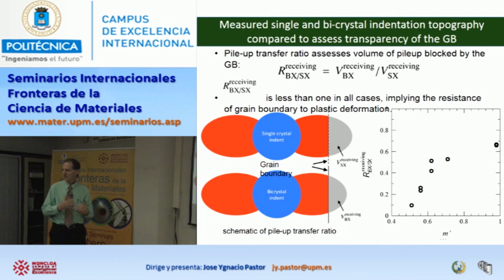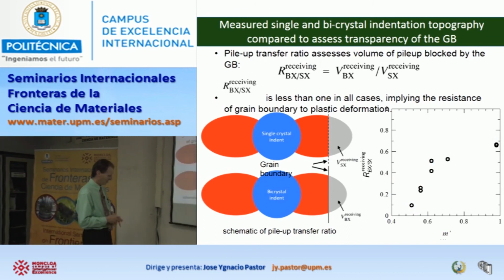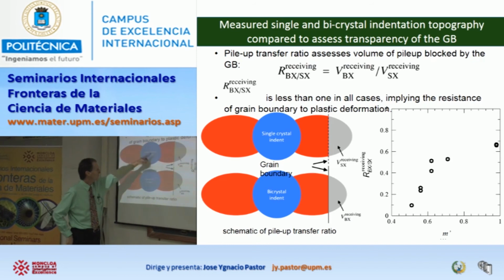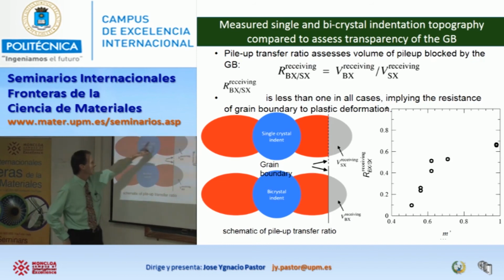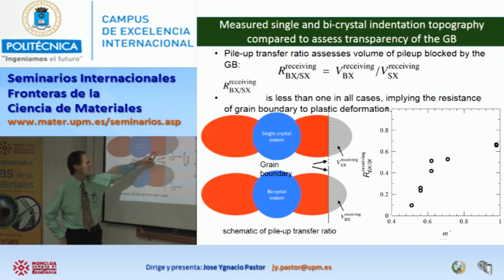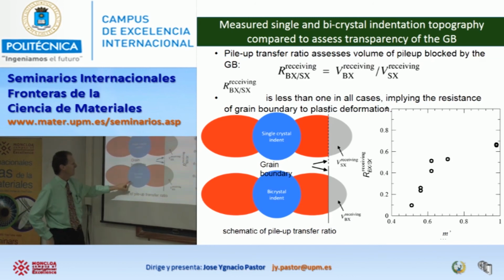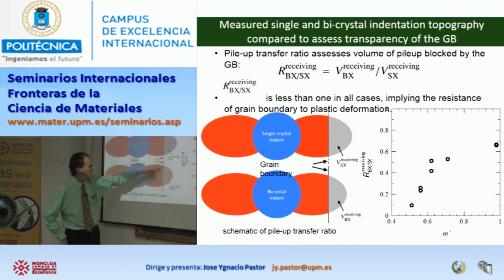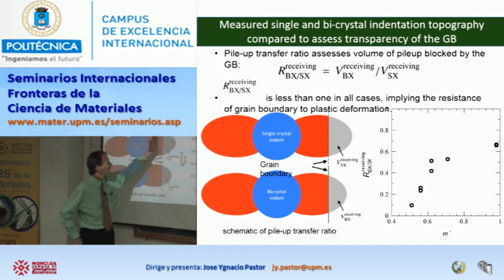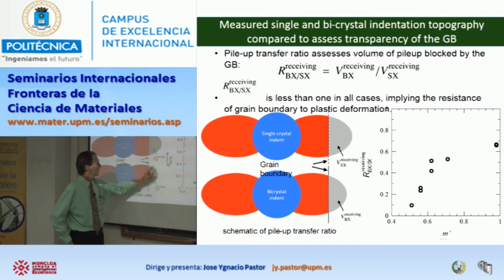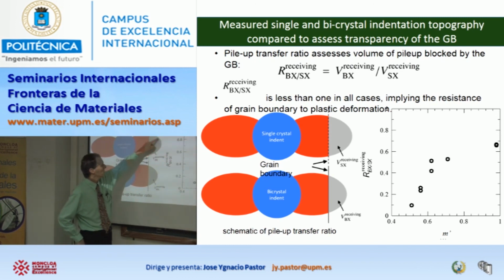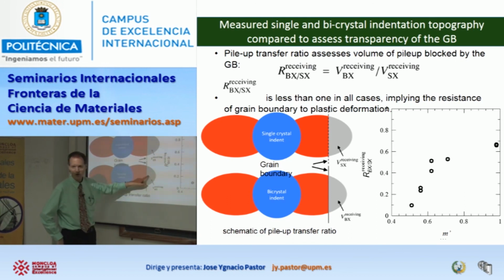And then we can ask some comparison questions. If I've got a single crystal indent, I have a geometry of the topography on either side. And if I compare that same indent with one on a bicrystal where there's a grain boundary right here, I could say that there's material on the right side which would be there as a bump, but it may not be the same shape of a bump if I have a grain boundary. So I can take the volume that has been pushed up here and compare it to the volume that's been pushed up here.